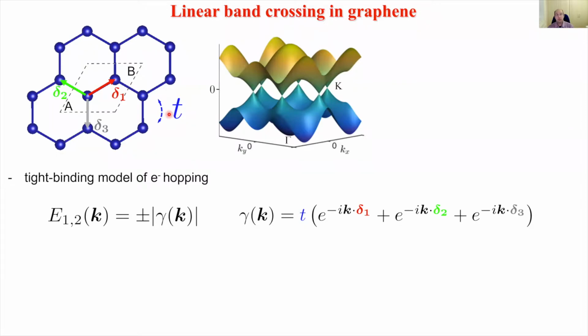And if we consider a tight-binding model to explain the dispersion relations of an electron that hops between these A and B sublattices, we find a relatively simple result. It's a modulus of this function gamma k, which is basically a sum of exponential terms associated with hoppings across the 3 links. Now, there are 2 dispersion surfaces that are mirrored with respect to 0 energy, and they touch